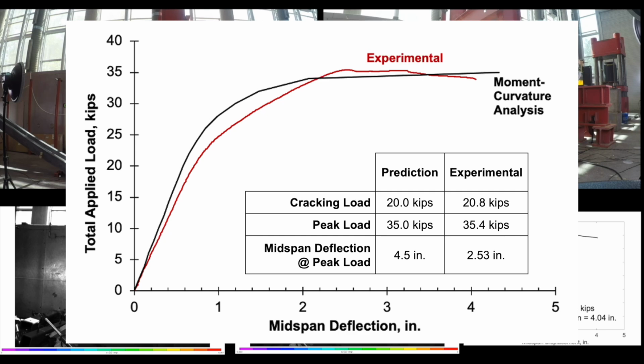The beam ultimately cracked at a load of 20.8 kips. It first peaked at a load of 35.4 kips, at which point the displacement was 2.53 inches. So how does that compare to our predictions? The answer, looking at our pretest prediction, is not bad, especially considering that the beam maintained the peak load through a displacement of 3.2 inches. We predicted a midspan deflection of 4.5 inches at a peak load of 35 kips.